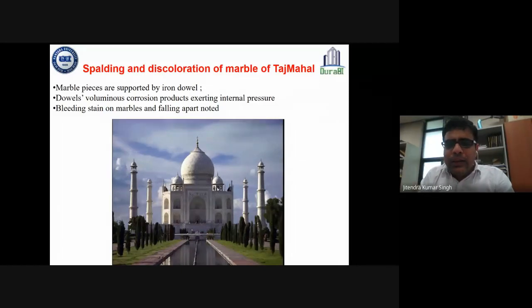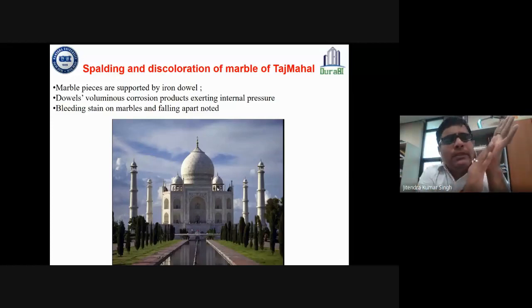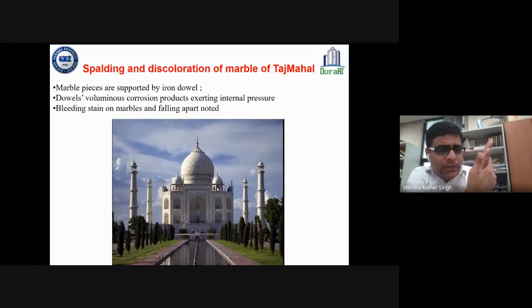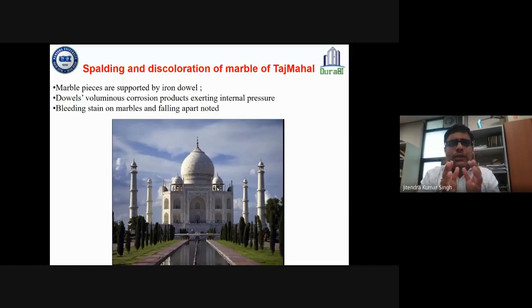If acid is forming in the atmosphere, the acid, meaning the aggressive ion, goes through some space, cracks, and pores in the marble towards the steel surface, and once it comes onto the steel surface, the corrosion will start. The corrosion product will cause some internal pressure on the marble, and through the spaces of the marble, the corrosion product is bleeding out. That's why some people are saying the Taj Mahal is bleeding. Bleeding means blood, meaning red rust. Red rust is coming. So they are saying the Taj Mahal is bleeding. This is not bleeding. This is the corrosion product coming from inside the iron dowel towards the surface.